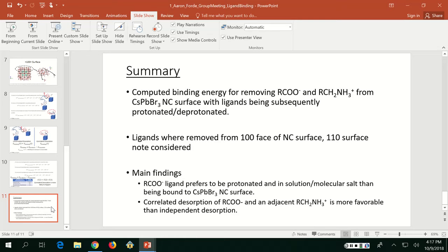If the surface of a quantum dot is missing ligand, it quenches luminescence immediately. It creates a surface trap. The charge will leak through the empty, uncovered spots on the surface, and it will stop emitting, so it will no longer be considered a good emitter. Therefore, there is a synthetic effort to prepare quantum dots carefully covered by ligands of this carboxylic nature.